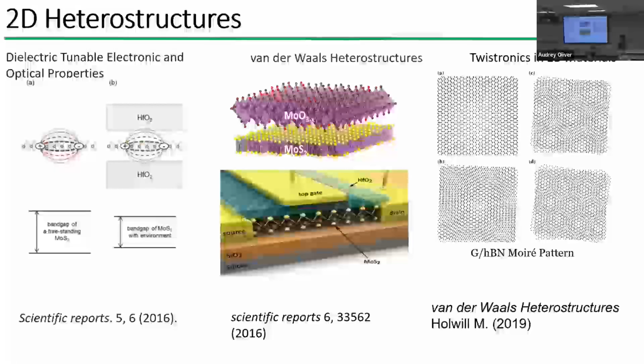The other thing is it's thin, having a single layer, so its properties will be different from bulk, right? Your electronic and optical properties will be different. For example, it will have a larger band gap compared to the bulk. And its properties also depend on its environment. If it sits on a hafnium oxide dielectric, the electron-electron interaction will be screened by that dielectric. That means it will change the electronic and optical properties, so you can see the band gap is changed, freestanding versus with this substrate structure. And that's what we published before.